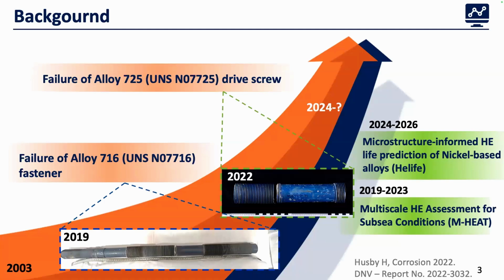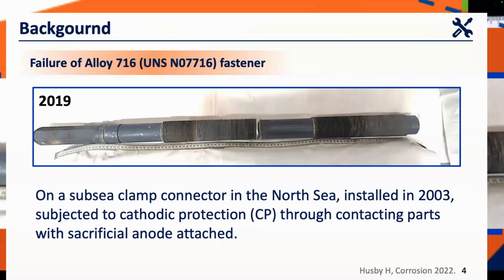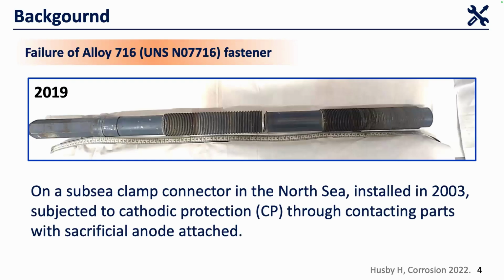So as we heard from Professor Jianying He in the morning, she presented that nickel alloys are intensively used in the oil and gas industries in Norway. And they have been considered as hydrogen-resistant alloys. But after some time, we can see the first report of failure in 2003 on the nickel alloys. And afterwards, several failure cases occurred. First of all, it happened in 2019, on a subsea clamp connector in the North Sea. This fastener was installed in 2003 and subjected to cathodic protection through contacting parts with a sacrificial anode attached. You can see this clear, sudden fracture of the fastener. And after investigation, it was proposed that it was caused by hydrogen embrittlement.